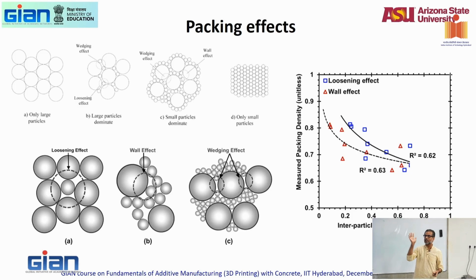Calcium hydroxide sticking along the aggregate particles and forming a zone of higher porosity, because you really can't fill things along a boundary well. That's the wall effect. You see that with aggregates as well. And then you have the wedging effect, right? This guy trying to squeeze in and create more distance. As a function of interparticle interaction, the loosening effect and wall effect create a reduction in particle density or packing density. This is what happens. Again, these are all simulated values that we have done.